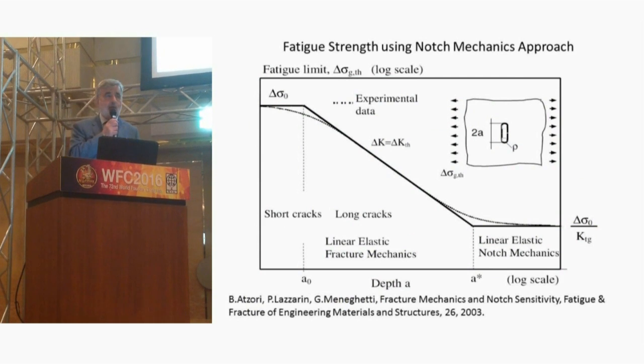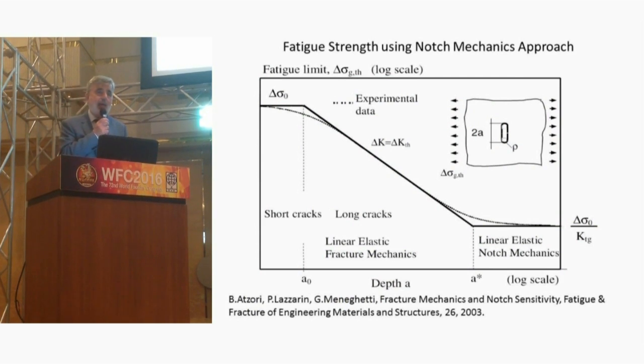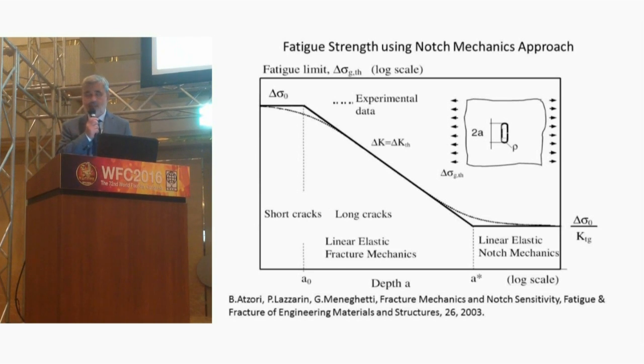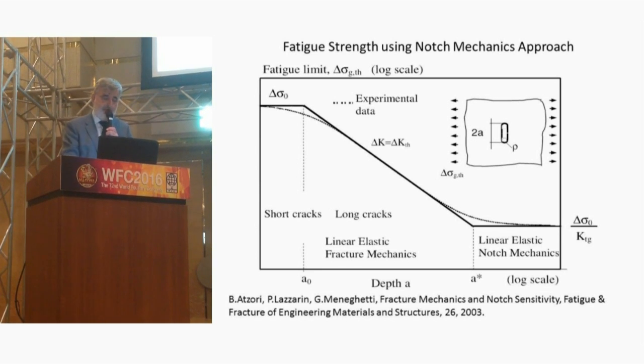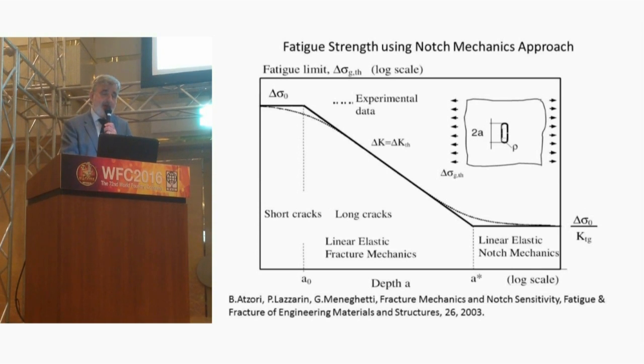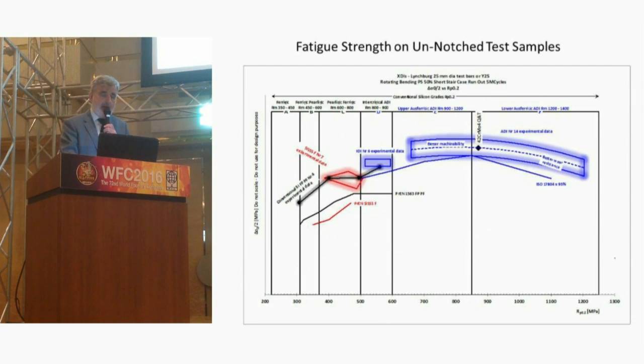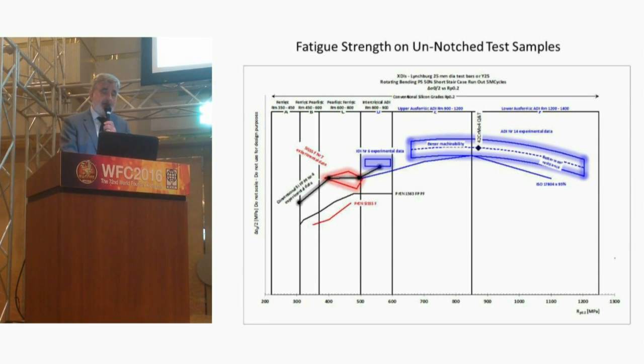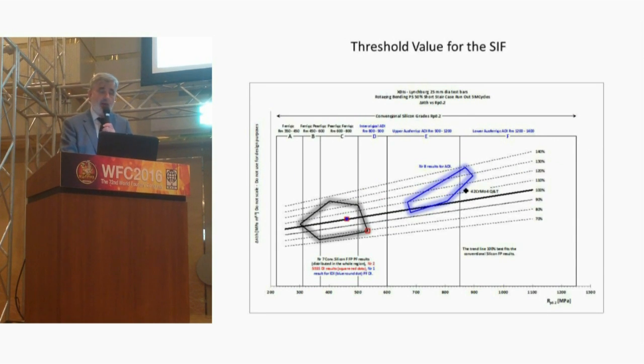So to change the Kitagawa diagram, to complete the Kitagawa diagram as taught by Padova University, which is assisting us in these matters, we can have first the unnotched fatigue strength, then the delta KTH, that is the oblique line, but the fatigue limit cannot always go under the full sensitivity. This diagram represents our experiments on all the irons that we tested, from ferritic, high silicon ferritic, ADI, and ausferritic ductile irons. The fatigue limits are notched, and this is also the delta KTH, the threshold value for all the